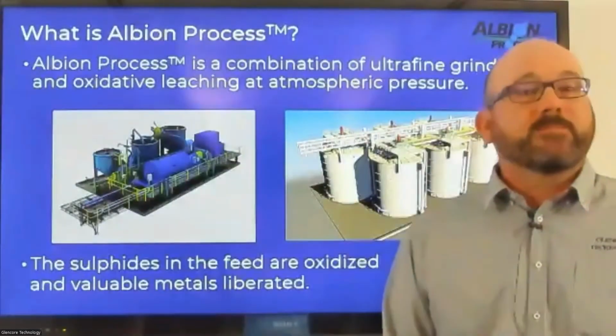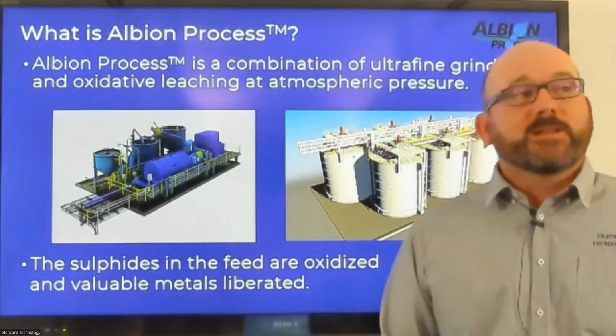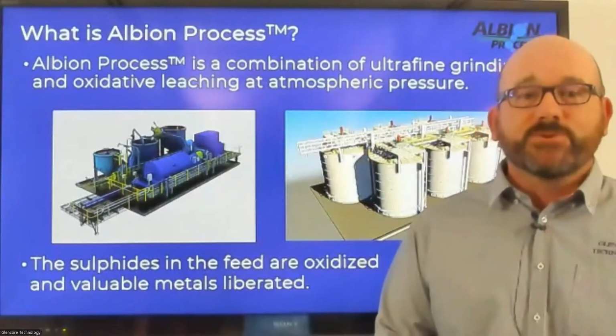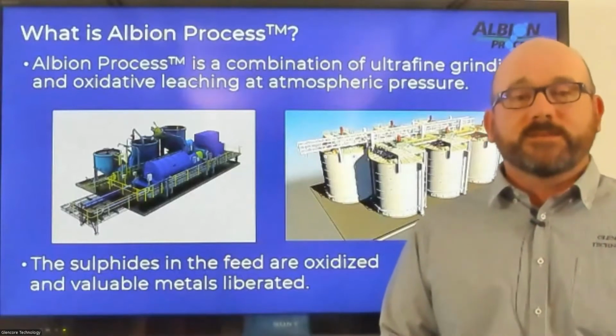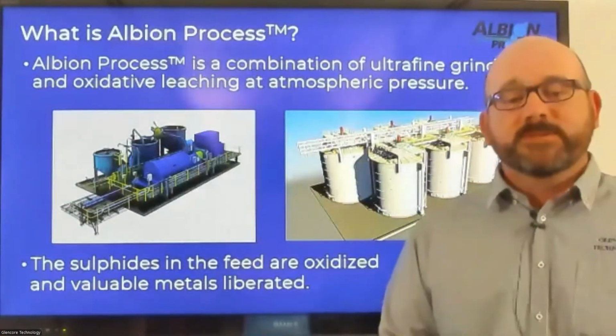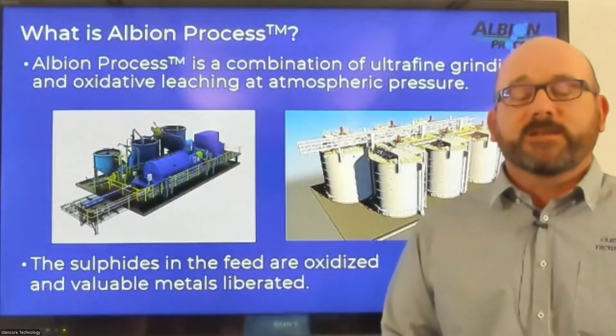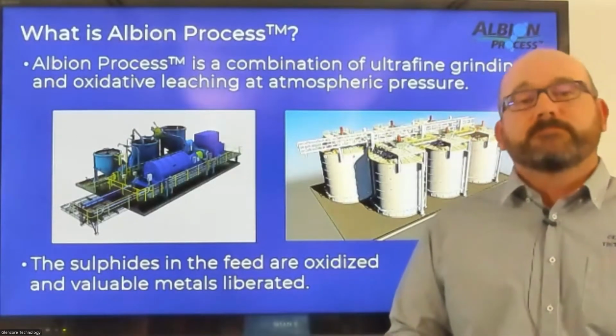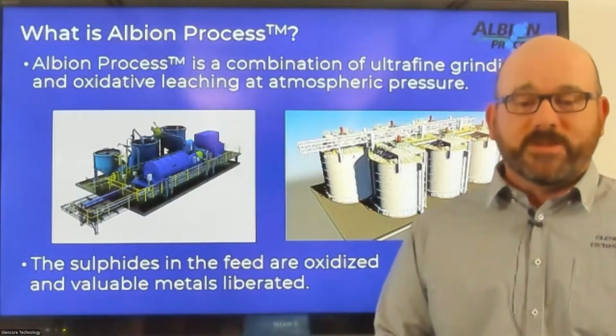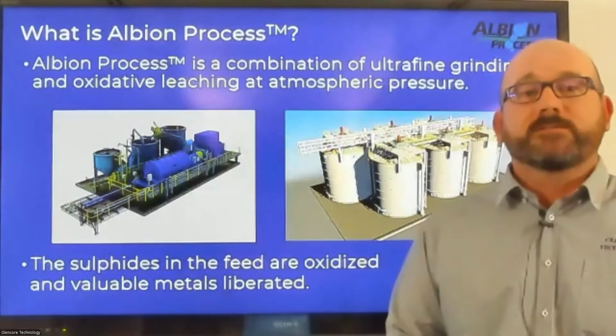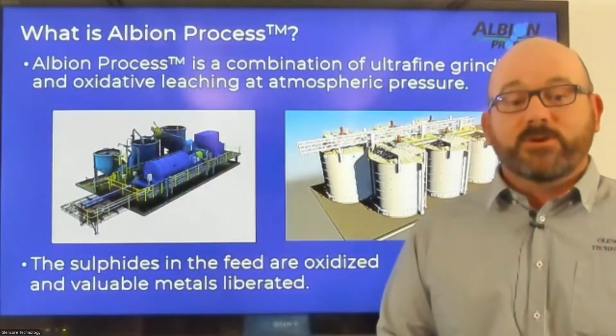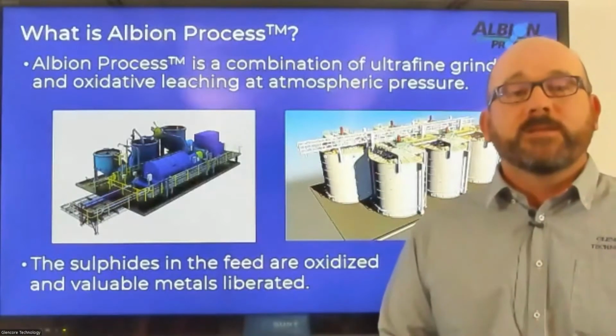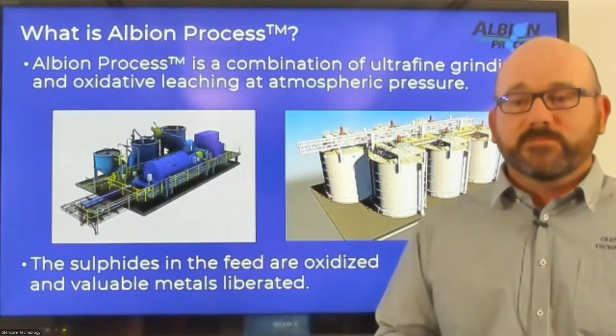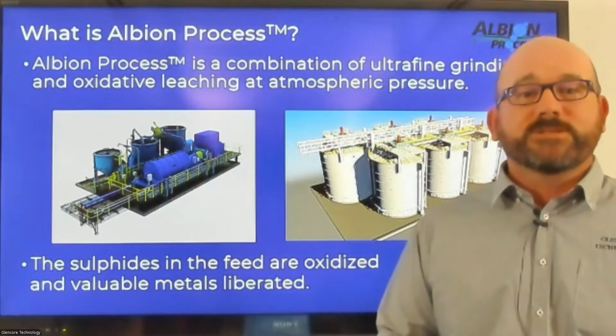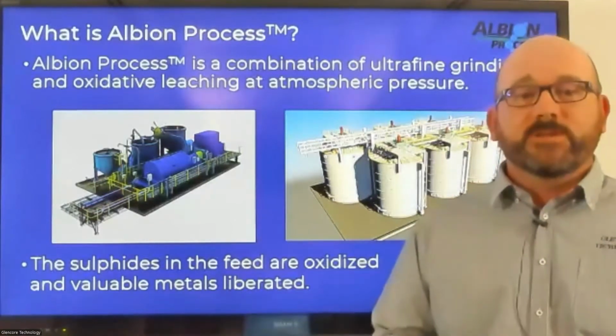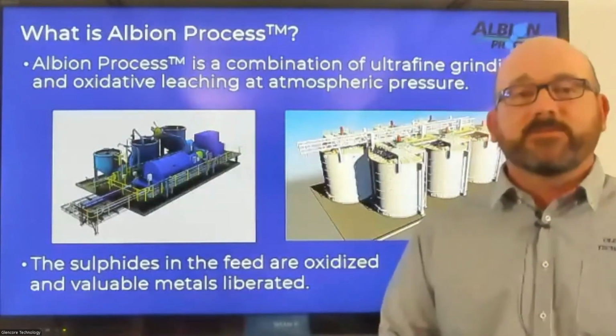So I guess starting in, what is the Albion process? When we're looking at the Albion process, it's a combination of two key things. One is the ultrafine grinding of the mineral particles, and then the oxidative leaching at atmospheric pressure. For the ultrafine grinding phase, we're looking at using our Glencore Technology IsaMill. It's a horizontal stirred mill using high intensity grinding. What this does is give us a really nice tight size distribution, so that we have really good characteristics for leaching in the second phase.